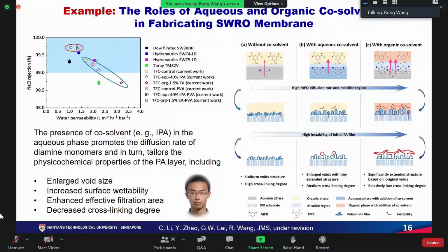Here, I give you another example, and this work is also done in my group. We tried to understand the role of aqueous and organic co-solvents in fabricating SWRO membranes. We found the presence of co-solvent in the aqueous phase promotes the diffusion rate of the diamine monomers, and in turn, it tailors the physical and chemical properties of the polyamide layer. So we can improve the membrane performance. And this work was done by my another PhD student, Li Can, and this manuscript is already submitted to the JMS. Currently it is at the first round of revision.